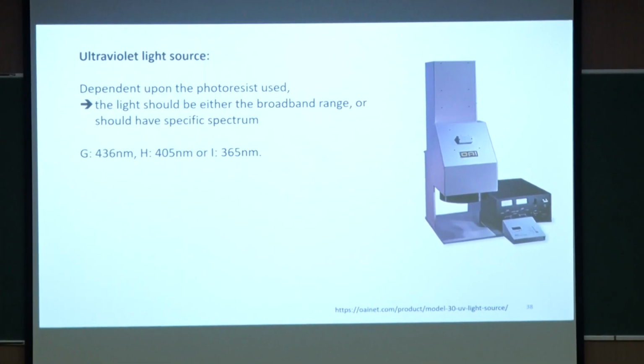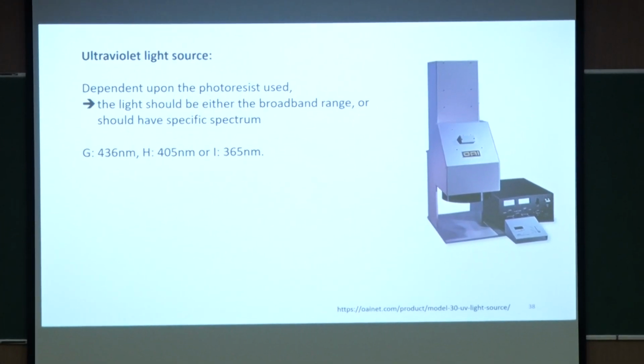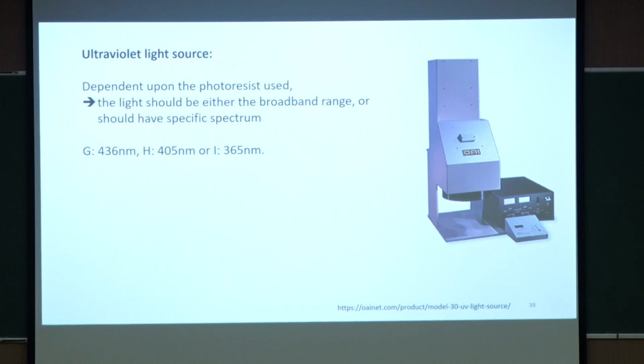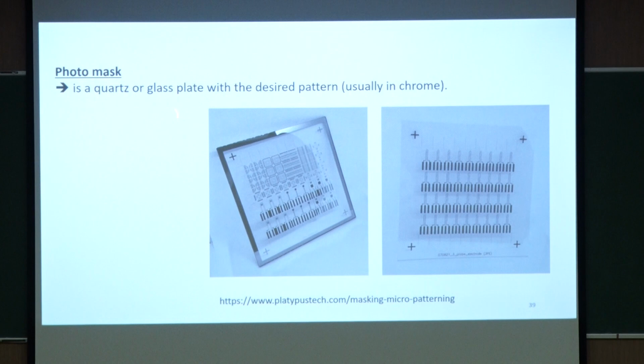Okay. Sometimes if your machine is not that sophisticated, it just exposes whatever the UV light is there, because probably the photoresist that you are using really doesn't care about that much, and your limitation of feature size is maybe around 2 micron. Generally you cannot go below that, okay, using the lab based technique. And photo mask, mostly you use a glass plate which is coated with chromium. Okay. So whatever the pattern here, that feature size you will get transferred 1:1, okay, kind of ratio. So, generally what you get is around 2 micron feature size with a hard contact.